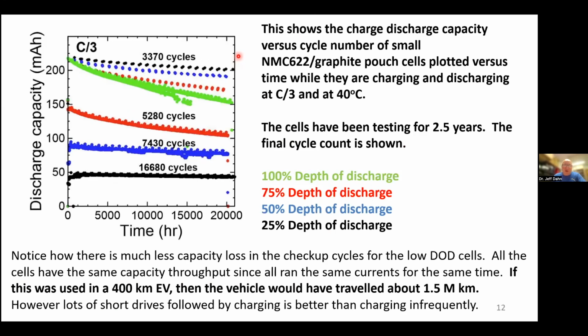So I want to show you how to avoid microcracking if you have a positive electrode material that is susceptible to microcracking. Here I'm showing a graph that shows, for a small lithium-ion cell, the discharge capacity versus time. 20,000 hours is about 2 1/3 years, roughly, while they're being charged and discharged continuously with a 3-hour charge and a 3-hour discharge at C/3.